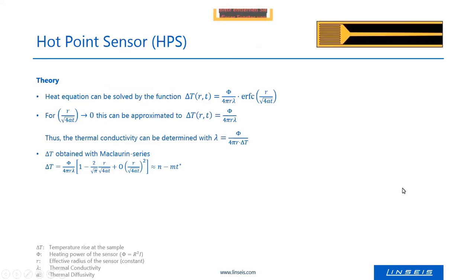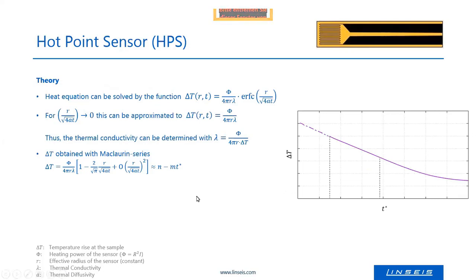Then the third kind of sensor, which we have in our product range, is a hot point sensor with a small measurement area, 2 by 2 millimeters. The theory behind it is a little bit different, but at the end, you have an equation where the delta T, so you measure, it's a simple thermometer like a PT100, you measure the temperature increase during the application of the heating current. And this delta T increases with 1/√ of the time. And by that, you plot the measurement curve, the delta T which you measure.